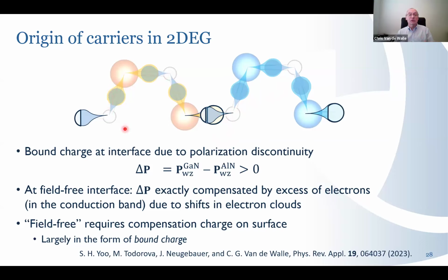Within the picture I was sketching for you, they come with the structure, because to explain the polarization in gallium nitride, we shifted the electron cloud a little bit to the left. To explain the polarization in aluminum nitride, you need to shift the electron cloud a little bit more to the left. And so at the interface, we end up with an excess of electrons over and above the 2 electrons that we need to form a bond. And all these electrons can do is go into the conduction band. This is where these electrons come from, okay? So they arise because of the shift in electron clouds that is intimately associated with the origin of the polarization.